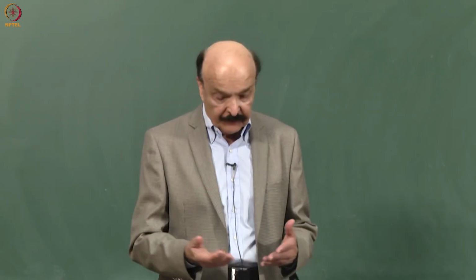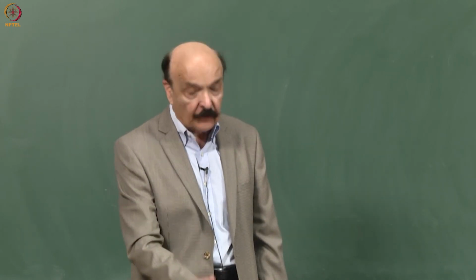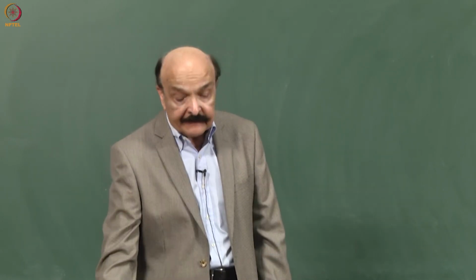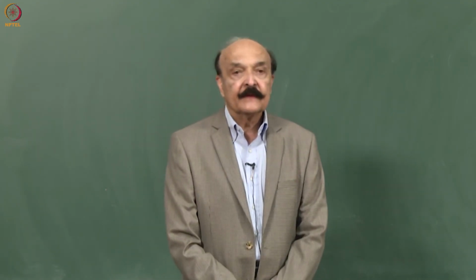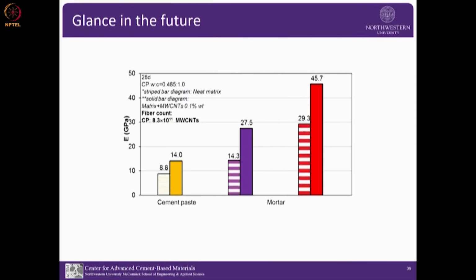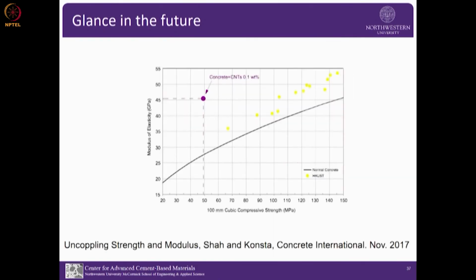You cannot model this with the composite material approach. Same thing more or less with concrete, and I will show you why. We thought this is quite interesting, so we plotted our results with concrete cylinder and 0.1%. This is the curve I showed you before, and we didn't really change much compressive strength, but there is a substantial increase in modulus. And if you want that modulus with the conventional approach, then you need that much compressive strength.